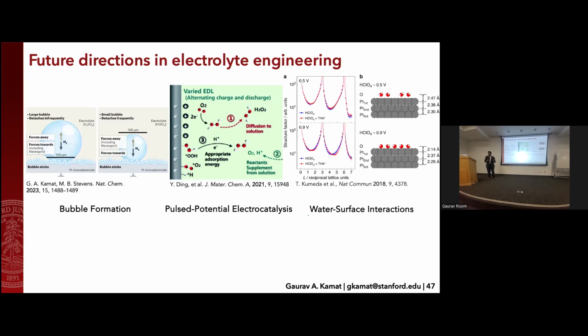I focused on anions specifically, but water also adsorbs to your surface. And there's other techniques such as the X-ray crystal truncation rod scattering shown here that actually let you resolve, well, in perchloric acid at 0.5 volts, I'm 2.47 angstroms away from the surface. And at 0.9 volts, I'm 2.14 angstroms away from the surface. It's that sensitive in terms of how you look at the water interactions.